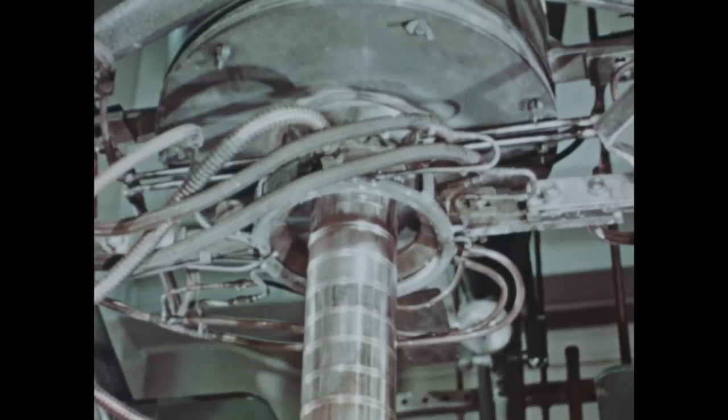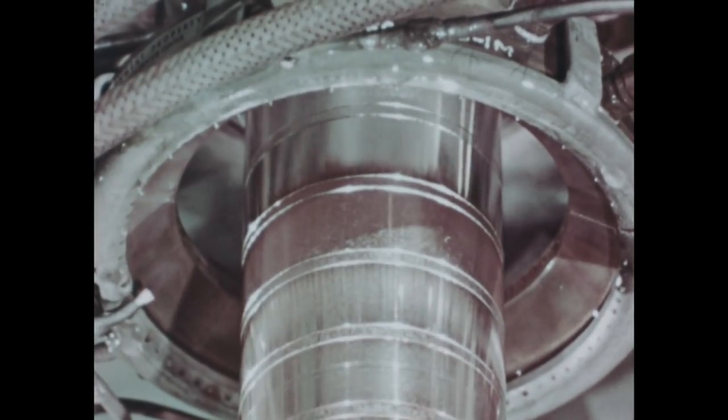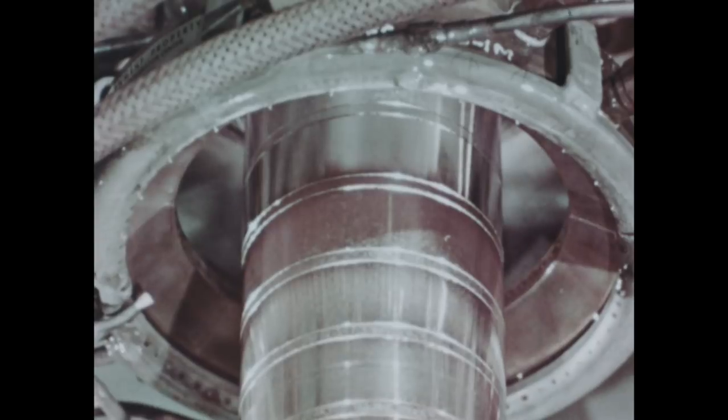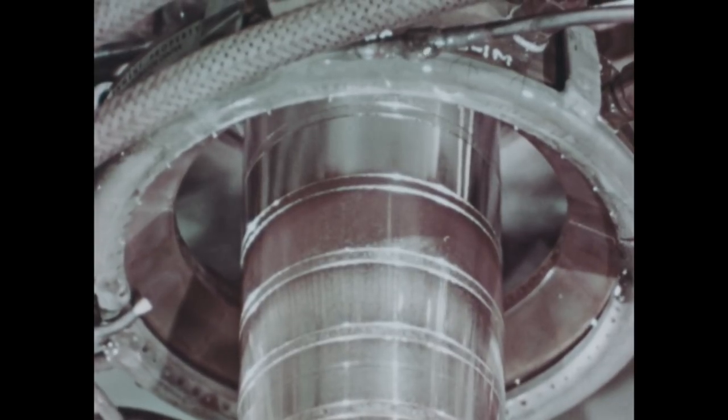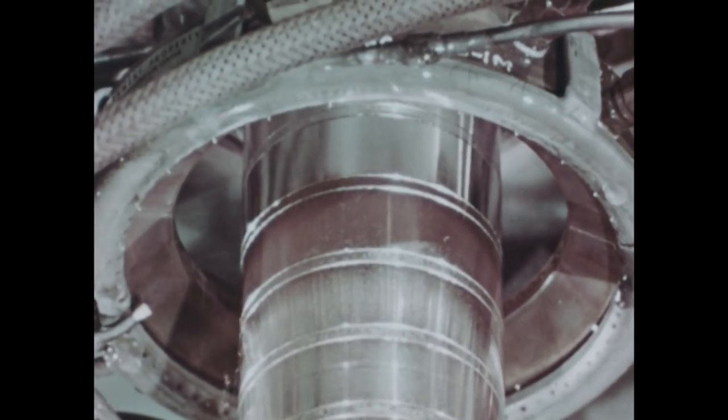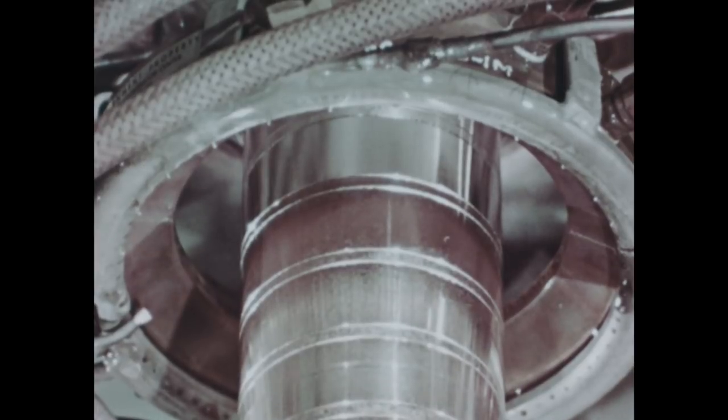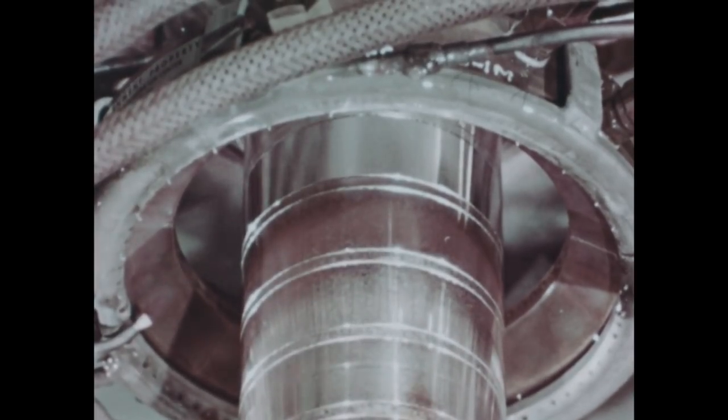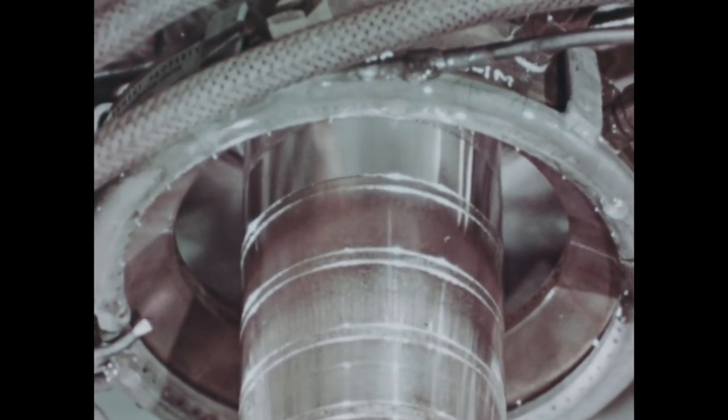Immediately after the braze, the pipe goes through the nose of the can and cools in the protective atmosphere. The liquid dripping from the ring burner is condensation, a byproduct of combustion between the hydrogen and oxygen. As the flame progresses down the pipe, there is no significant evidence of oxidation below the burner and absolutely none above the burner.